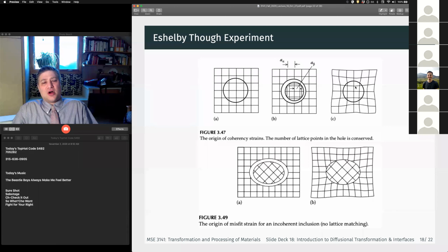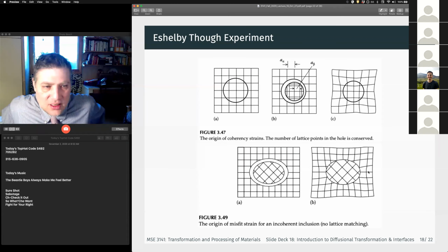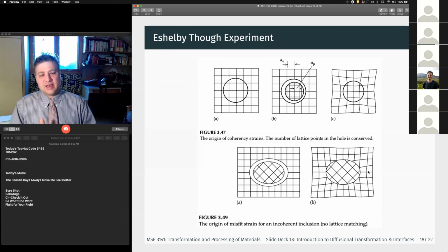But this is a really useful thought experiment to think about how the lattice is going to distort. So in this case, we maintain a coherent interface. We have our one-to-one correspondence. We can work through the same exact sort of thought process for an incoherent interface. Now we don't have the same correspondence. And so if we think about what is going to happen with the shape of the precipitate, it's going to be determined by a combination of the interfacial anisotropy and the anisotropy of the elastic stiffness.